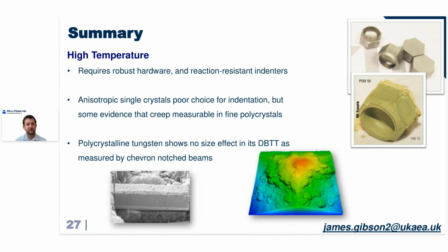I've shown you from the superalloy studies that anisotropic single crystals behave very strangely in indentation. It takes a while. You have to be aware of them. But there is some evidence that at very high temperatures, where you have significant primary creep, you can get real creep data out of fine polycrystalline materials. And you've just seen that when we do these tests on tungsten at higher temperature, there's no size effect in its ductile brittle transition temperature.